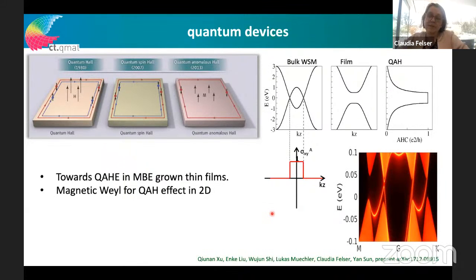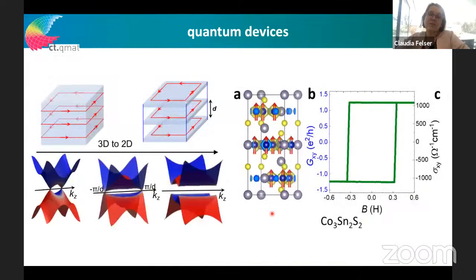So we thought this is worth a try, but it's not as easy as graphene. We cannot scotch tape this material, so we are still working hard on making it more 2D. But what we already see is, if we think about how big the Hall effect is per layer in our material, we come very close to the quantized value of 1.